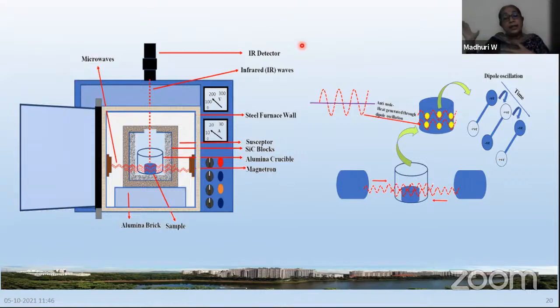Whereas in conventional sintering, if 1250 is your final sintering temperature, usually the ferrites are kept at 1250 degrees centigrade for a minimum of 2 hours to a maximum of 6 hours, depending on the material characteristics you are taking. So a minimum of 2 hours is definitely required, and that is called the soaking time.